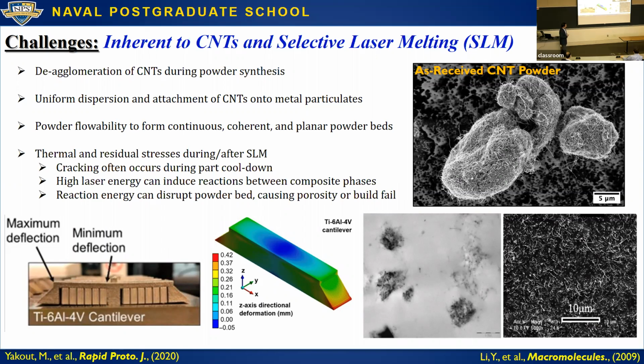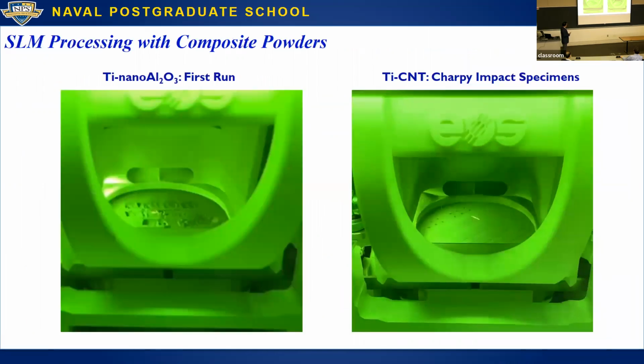If you do end up with CNT agglomerates in your final structure, so this is a TEM image showing clusters of CNTs in your final metal matrix composite, you actually can lose a lot of the benefit of the CNTs. This cluster is not going to provide a lot of strengthening. In fact, just the opposite. Within the cluster, you may actually have enough porosity that they can serve as a defect site. So that's why you have to be very careful when you're processing these materials. Dispersion and getting a good quality starting powder are quite essential to being able to get a useful end product.